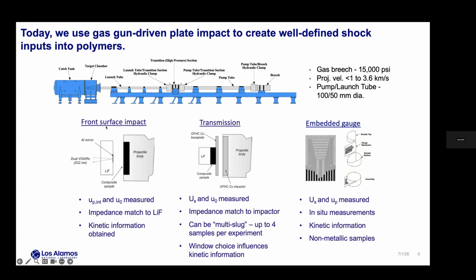So typically we employ a front surface impact geometry where we might impact the polymer into a window. That's kind of our easiest experiment for getting a Hugoniot state. And you can also get some temporal information from the wave profile at the interface. We do a lot of transmission experiments where we launch an impactor into a drive plate, much like you saw in the plane wave lens experiments. And then we observe the shock wave going through the sample, again, typically at a windowed interface. And so we can see how that wave evolves over time and distance.